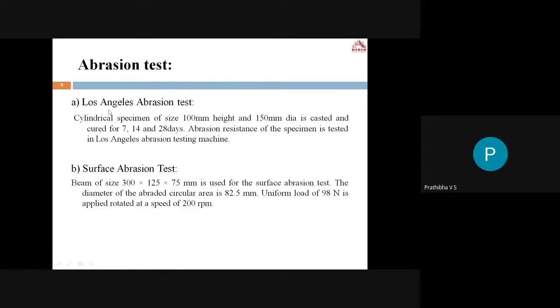So next is the abrasion test. We have conducted the abrasion test in 2 different methods. One is the Los Angeles abrasion test, and the second one is the surface abrasion test. In the Los Angeles abrasion test, a cylindrical specimen is used with a height of 100 mm and diameter of 150 mm. It is tested for 3 different curing durations, that is 7, 14, and 28 days of curing. The cylindrical specimen is inserted in the abrasion machine and rotated for around 500 revolutions, and the difference in the weight gives the wear and tear of the material.